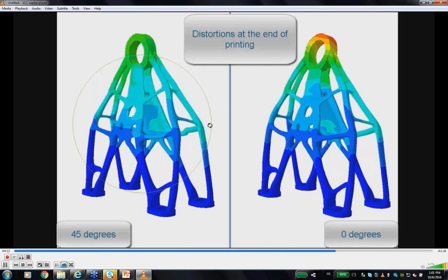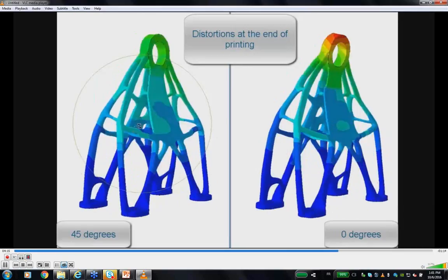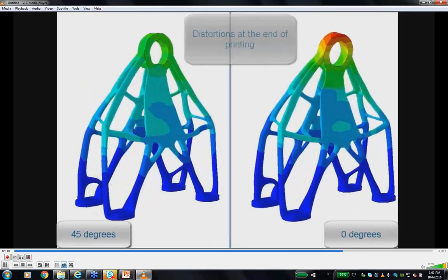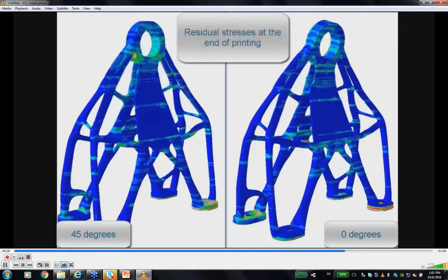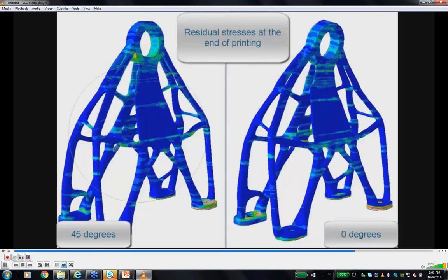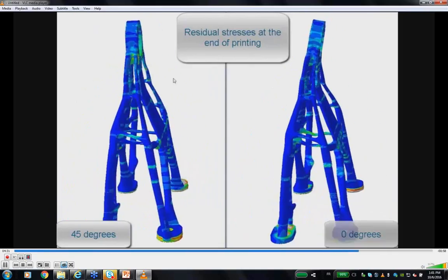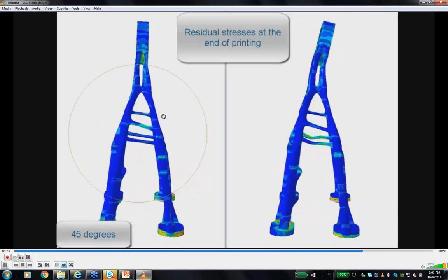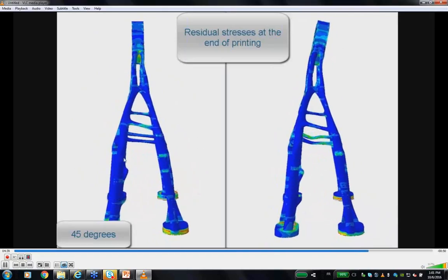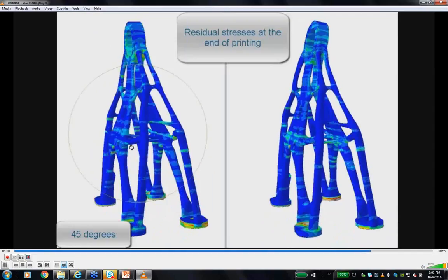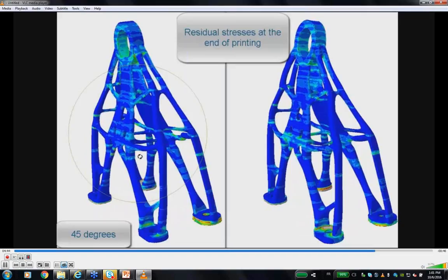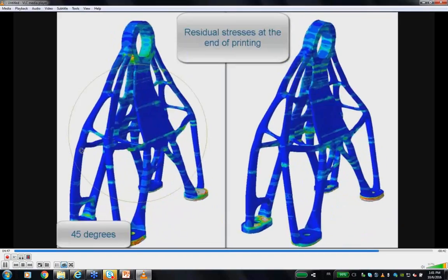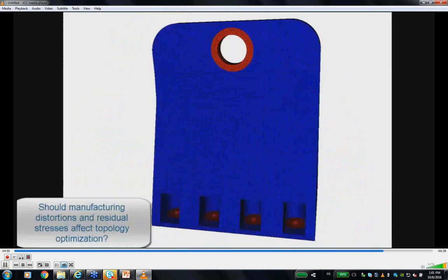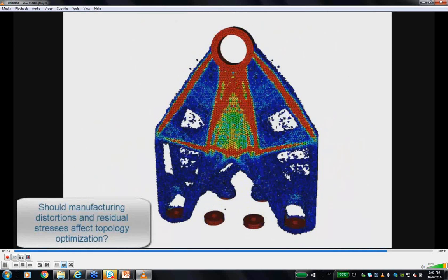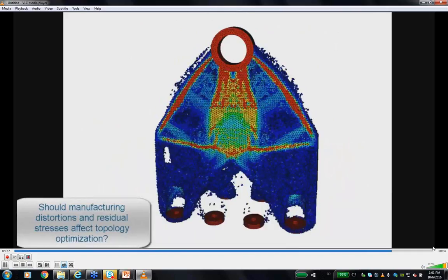And as you can see, I can simulate what will happen during the process. I can have an idea of the distortion of the part once it is printed, and I can really reduce the risk of a failure on the machine. For those who are not familiar with the printing machine or printing process, if you take a part which is 100 millimeter high and a diameter of let's say 100 millimeter, it can take 100 hours to print. And if after 100 hours of printing you see that the part is not within the specification and then you have to throw it to the garbage, it's not good news. Okay, so it's very important to simulate as much as you can upfront, and this is exactly what we do.